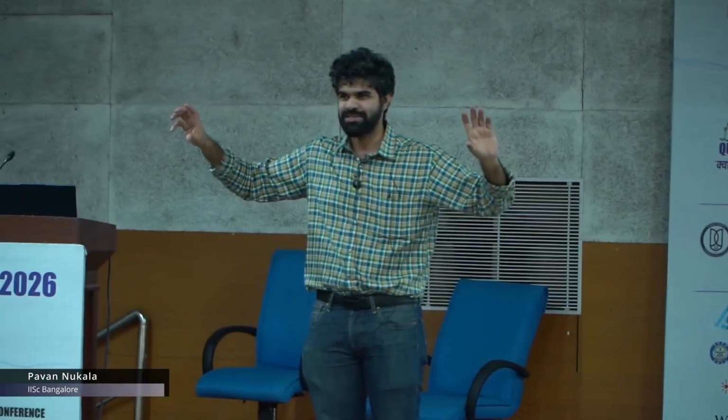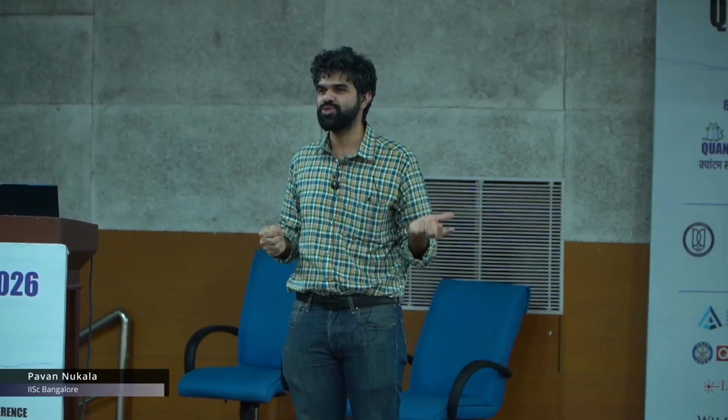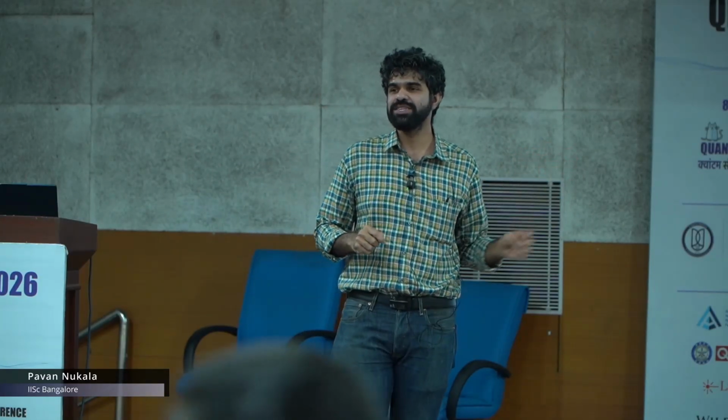How do you get back from the amorphous state to the crystalline? You just have to send in enough current. That's a very good question, because if I have a long device, I cannot do it. I have to send in enough current or current density that heats up the amorphous phase back to a crystalline phase. So we make very short channel devices, about 500 nanometers or less, and by applying a reasonable voltage, you can send in large current, so that actually the crystallization is a more energetic process here than amorphization.